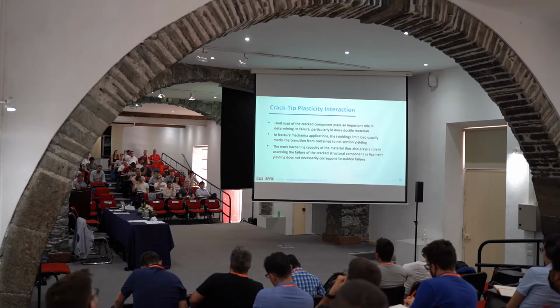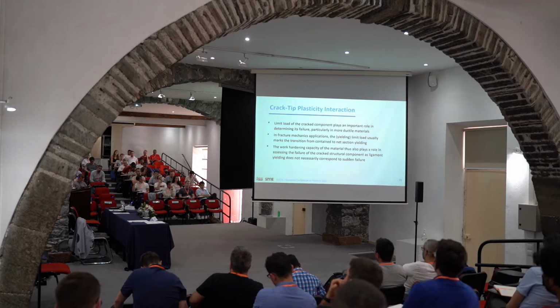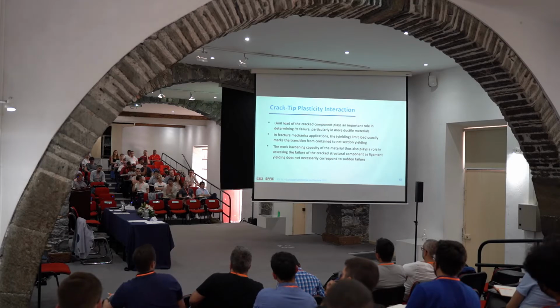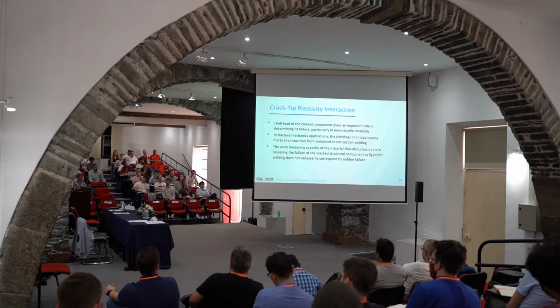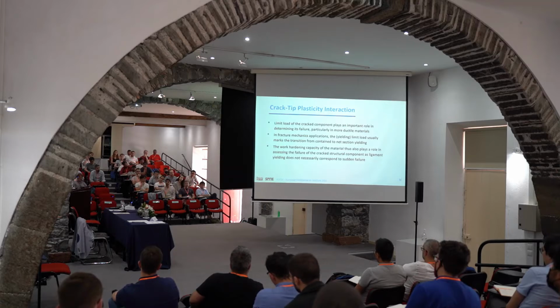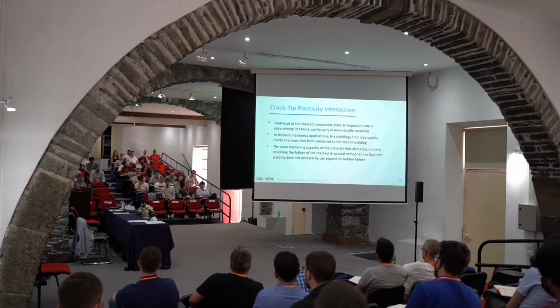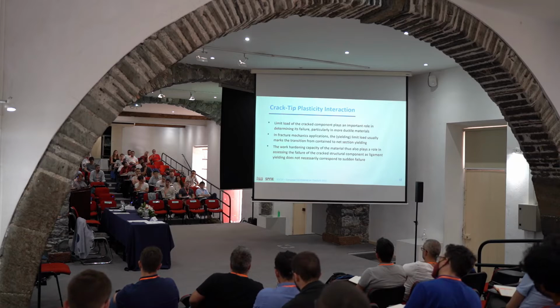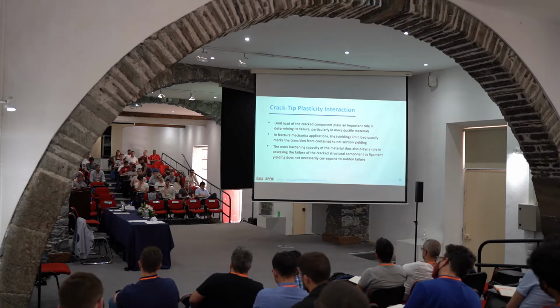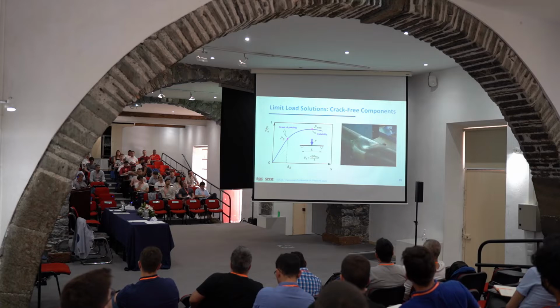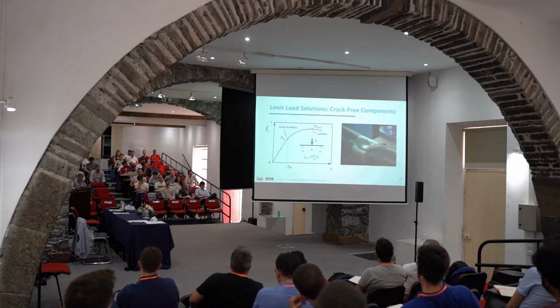Okay? And here comes the plasticity interaction. It's important because the limit load of the cracked component plays an important role in determining its failure, especially in more ductile materials. And this is very important nowadays because, again, I'm talking about metallic materials, in particular steels. The steels are getting much better, with higher strength and much higher toughness compared to what we had 20, 30 years ago. And the limit load is defined from, I'm not going very much into detail, a limit load analysis.